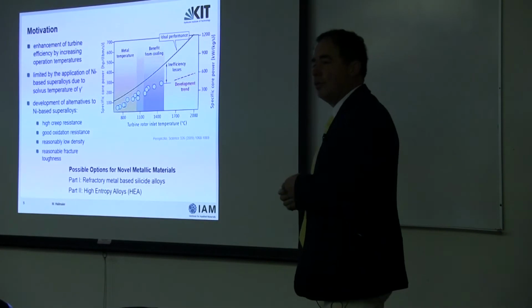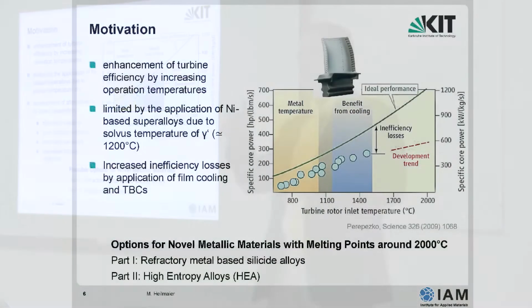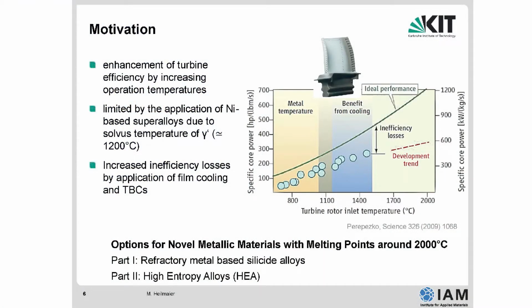And this is simply due to one fact, namely that the alloys which we currently use, the nickel-based alloys, are limited by their Solvus temperature of the strengthening phase gamma prime, meaning we reach the maximum operation temperature of these alloys. We need to develop new materials, alternatives to nickel-based superalloys, which have a much higher melting point, and thus provide high creep resistance, oxidation resistance, and other properties.